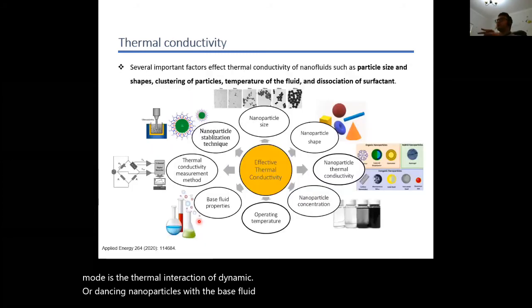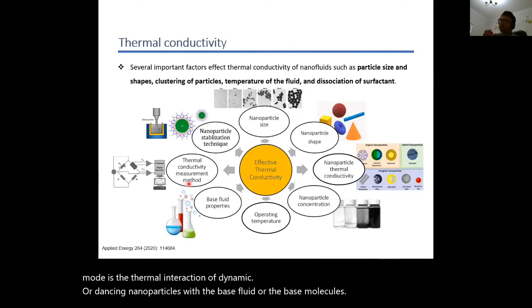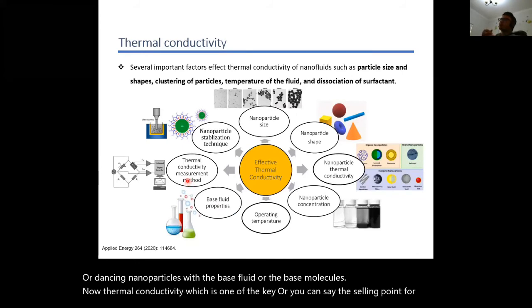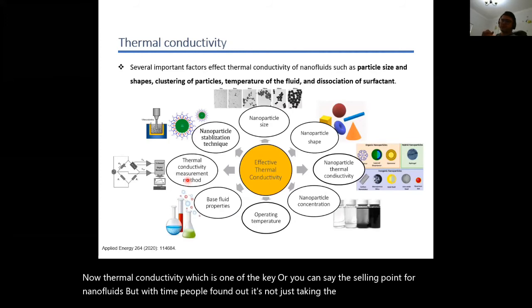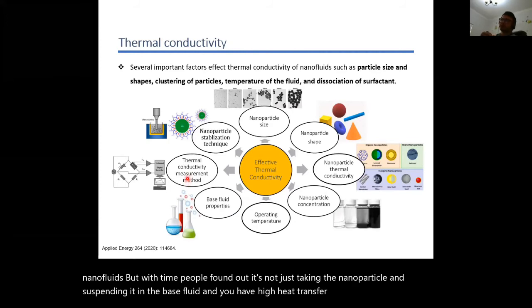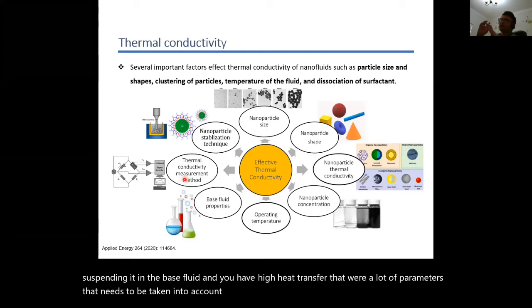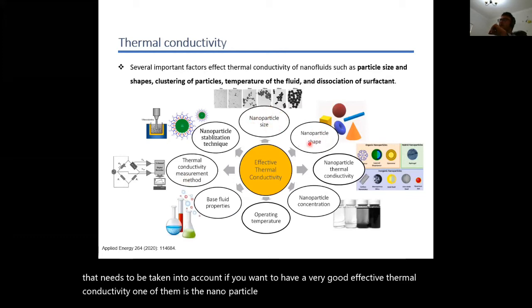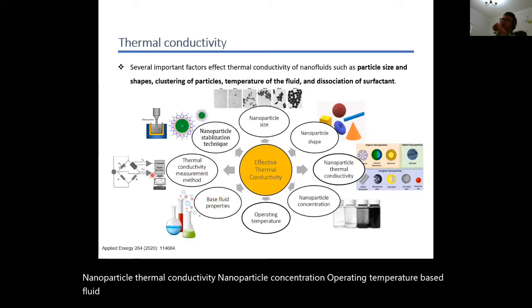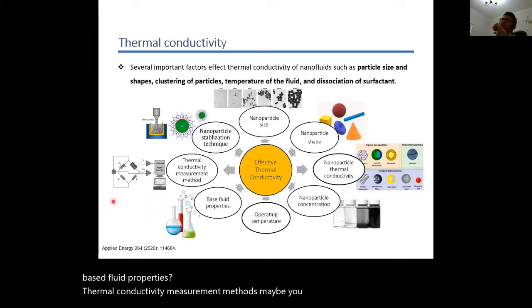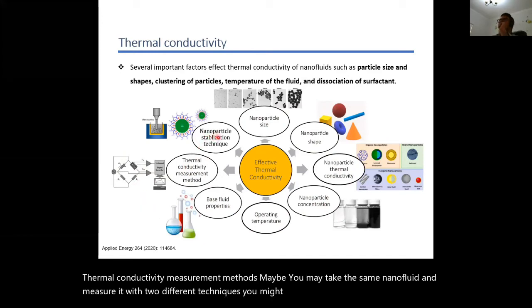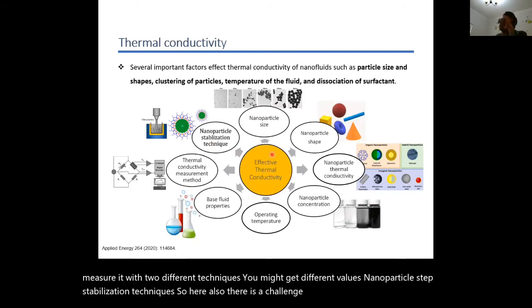Now, thermal conductivity is one of the key, or you can say the selling point, for nanofluids, but with time, people found out it's not just taking the nanoparticle and suspending it in the base fluid and you have high heat transfer. There are a lot of parameters that need to be taken into account if you want to have a very good effective thermal conductivity. One of them is the nanoparticle size. Second is the nanoparticle shape, nanoparticle thermal conductivity, nanoparticle concentration, operating temperature, base fluid properties, thermal conductivity measurement methods. Maybe you take the same nanofluid and measure it with 2 different techniques, you might get different values. Nanoparticle stabilization techniques. So here also there is a challenge right away. I'll discuss it here. No need to discuss it later.